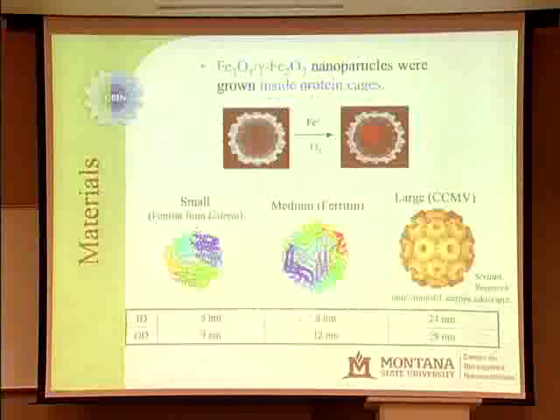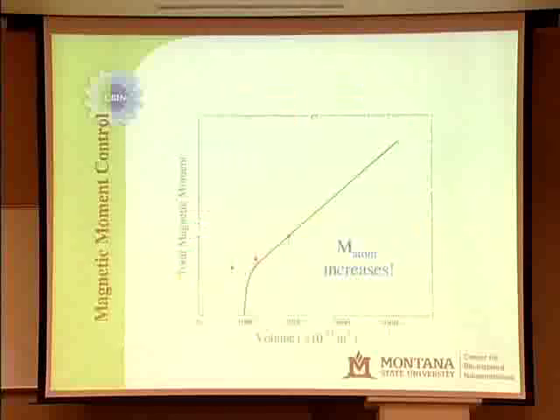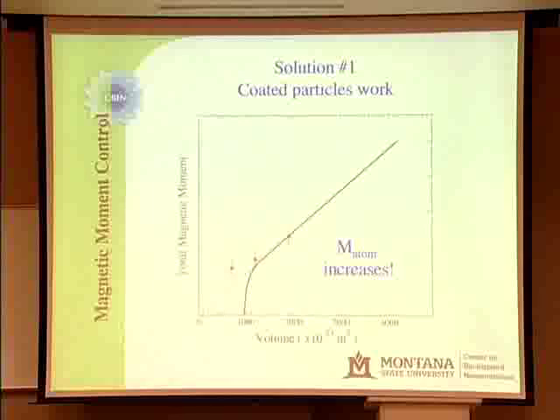We used listeria ferritin, horse spleen ferritin, and something called CCMV, which I'm not going to go into the whole name of what that virus is. They're just different sizes. Some of them are 5 nanometers, the inside region, 8 nanometers, 24. Those are the three that we used in this case in order to vary the size of the particles. And when we did that, we found the particle moments went up like they're supposed to. So the solution was that by coating the particles, we made the moment do what it was supposed to do.